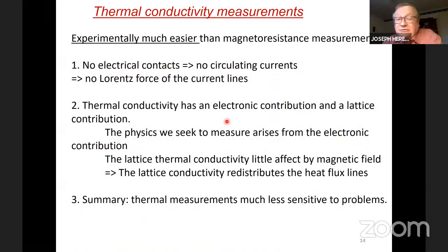So that the problems with misalignments in sample geometry and all problems that are due to current line distortions are much weaker, much smaller in thermal measurements than they are in electrical measurements. And frankly, this makes the thermal measurements much more reliable and much easier. And I will show you how much more reproducible they are, whereas the electrical measurements are not. They take tremendous care.